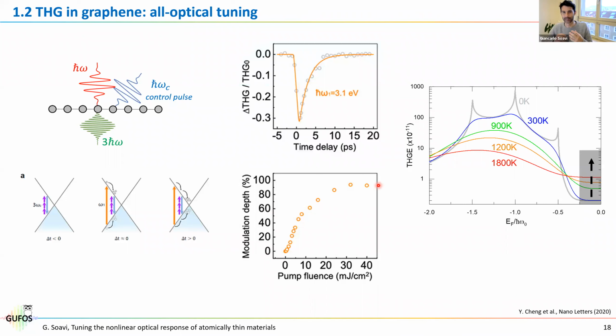However, there is a trick, there is a problem in this experiment that doesn't fit with the theory. If you now look at the value of the Fermi energy that was used in this experiment, they are working in this region. So it's small values of the Fermi energy. So in this context, we would expect that as you increase the electronic temperature with your control pulse, then the third harmonic efficiency is increasing. So this curve should not go negative, but it should go positive instead. So this is somehow controversial.